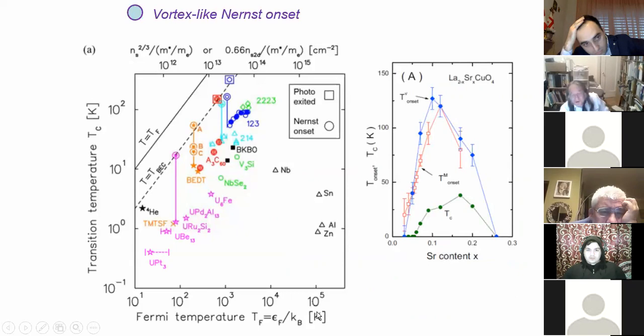Okay, so what I recently noticed is that you can plot the onset temperature of this Nernst effect or small diamagnetism as a function of Fermi temperature. This charge energy scale can be measured by μSR, and the onset temperature of the Nernst effect can be measured by the Nernst effect. So you can plot the onset temperature, not the real TC, but the onset temperature of the Nernst effect, in this plot. And if you do that, the data for lanthanum strontium copper oxide comes here. This circle is showing the Nernst effect onset. You see, it's about 4 times higher than TC. So the TC is here, and it's 4 times higher, and it's here.